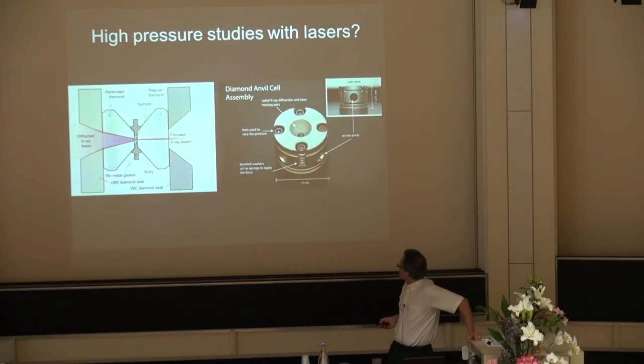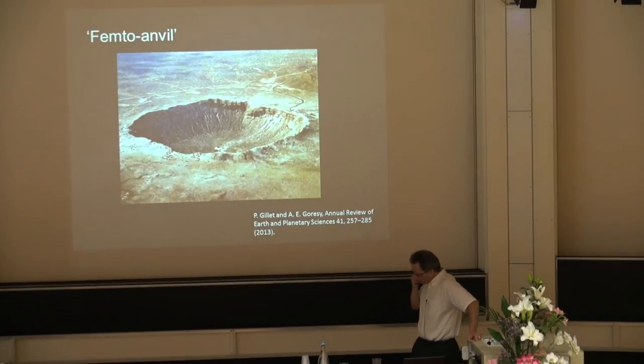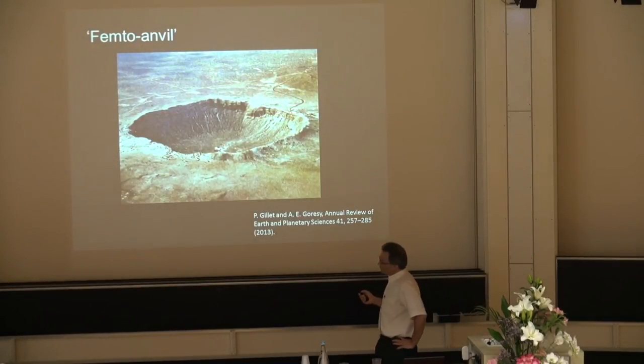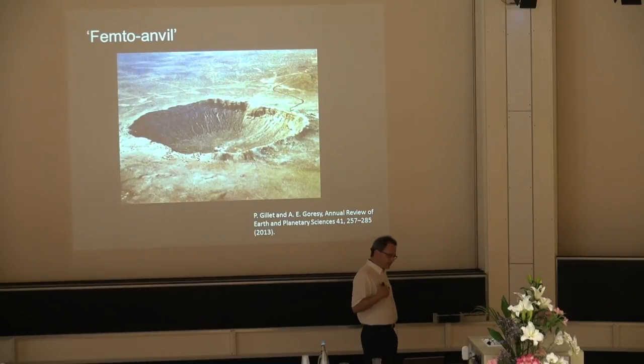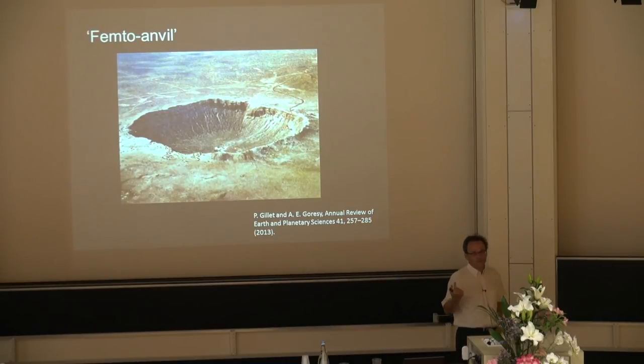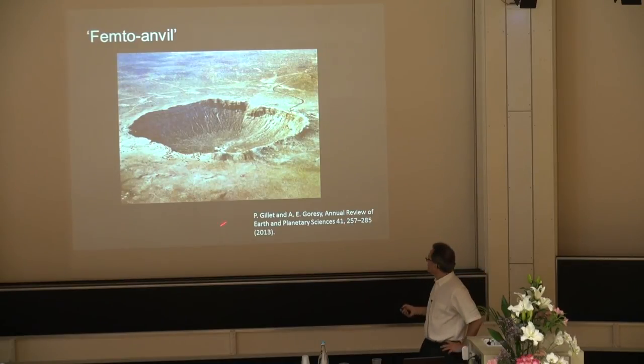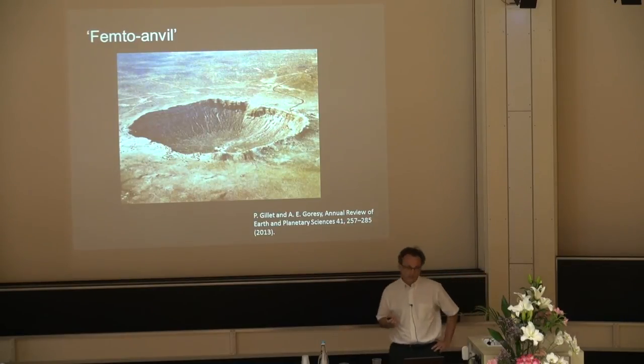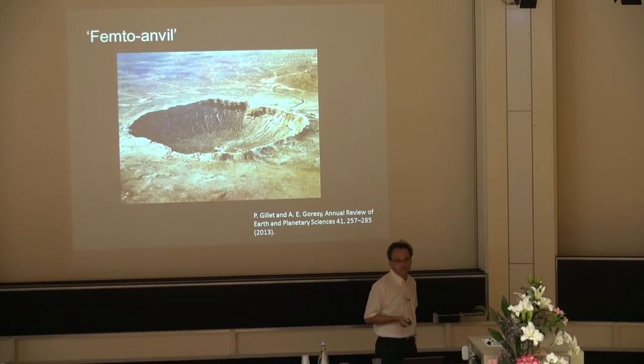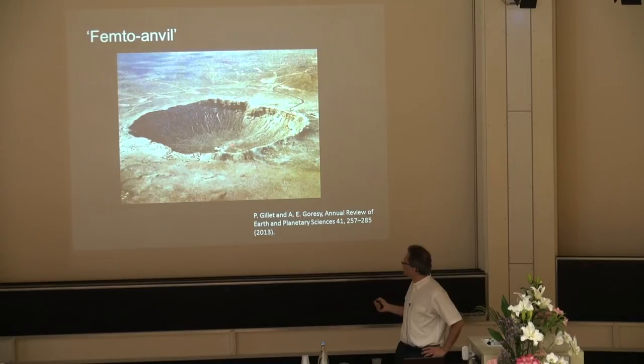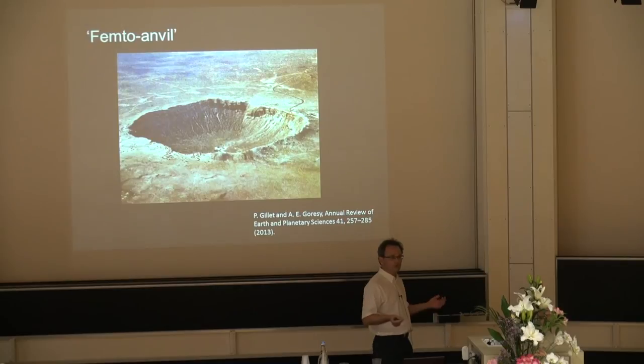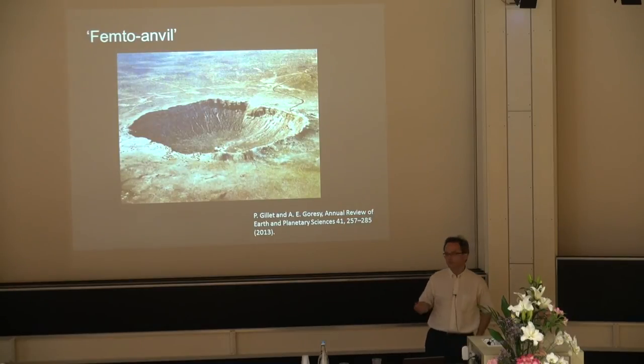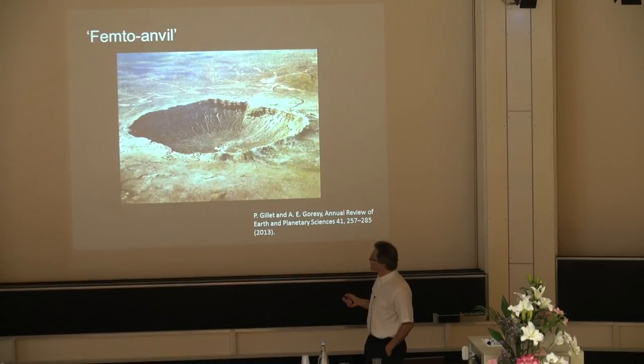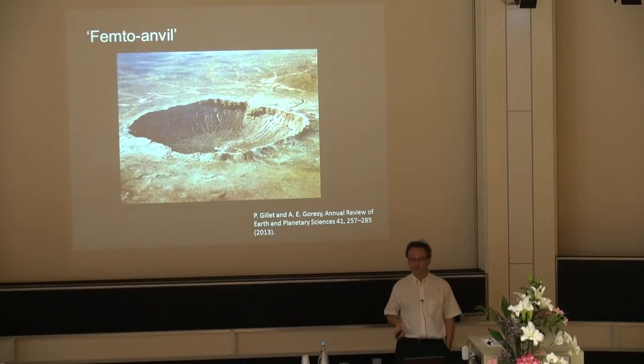Now, imagine that maybe we could mimic some of this with a laser. Why would that be interesting? It's because we know that at high pressure, there are certain phases, for instance in the case of silica, that form and that have been found in nature. For instance, stishovite, which is a very well-known phase. It's one of the hardest phases on Earth, but it has been found only in certain areas, for instance in meteorite craters, because the shock was so violent that it created the conditions where the material could form. And this material, stishovite, has a density which is twice that of the initial glass. It's like 4,000, it's incredible.